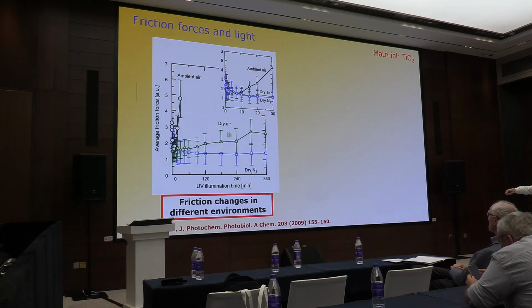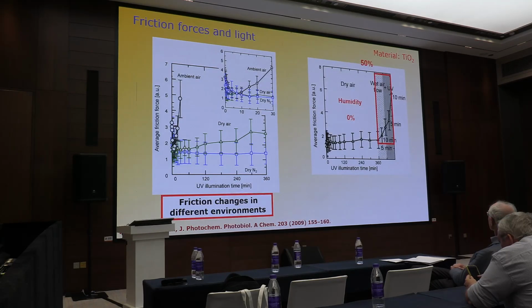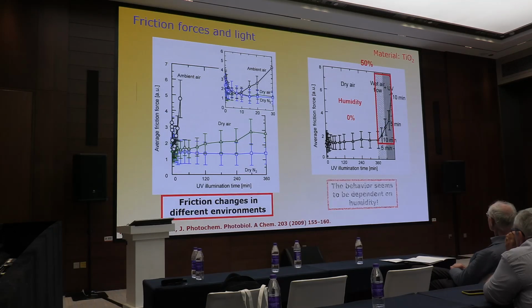In this case, with the illumination, you can see that the friction force is increasing. There is an effect here. It is constant in dry nitrogen, but increasing in dry air. It's not so clear, but the effect is there. In the other one, you can see that the effect is higher. This is wet air plus UV, and the behavior is more clear. Maybe I would put 50% of modification, something like that. Here there is a more clear effect. The behavior seems to be dependent on humidity as well, on water content.